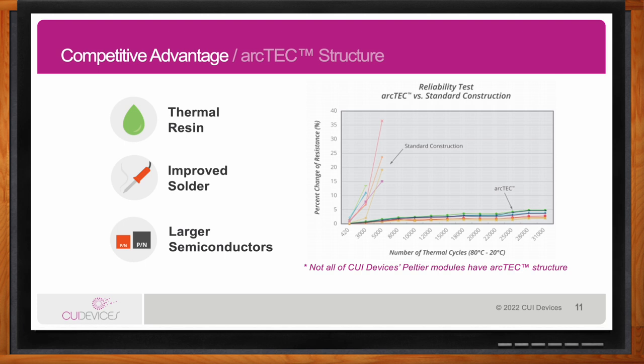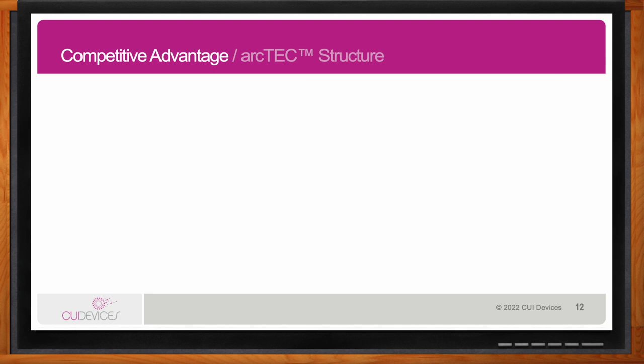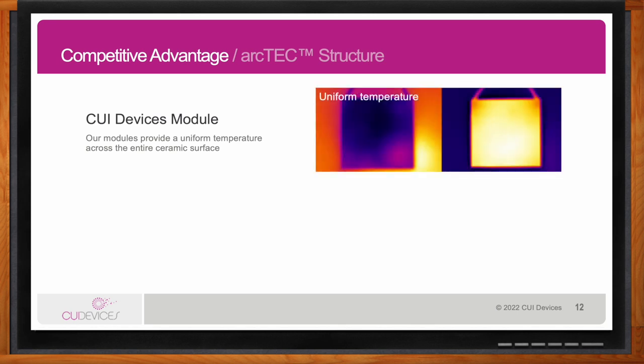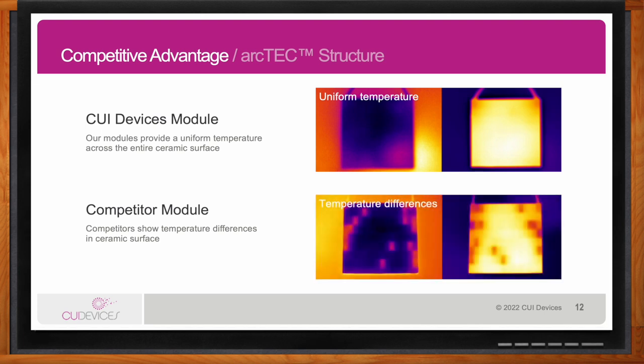I see. So how does the CUI devices module compare to similar devices on the market today? Yeah, so aside from the thermal resistance change that I mentioned in the previous slide, we use particularly large semiconductor pellets inside of our Peltiers. What this does is it creates a uniform temperature across the surface of the Peltier module. As you can see in these images that we took with a thermal camera, the top pictures are a CUI devices module, and you can see that the ceramic is essentially the same temperature across the entire surface. That is due in large part to the larger pellets that we use inside of our modules.